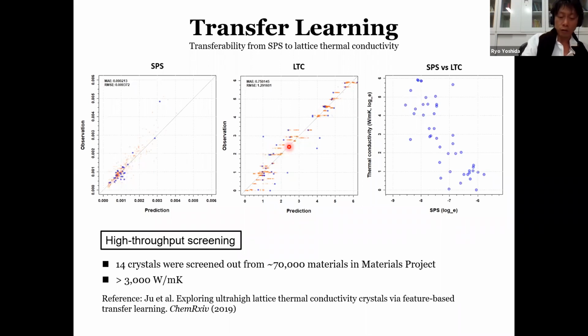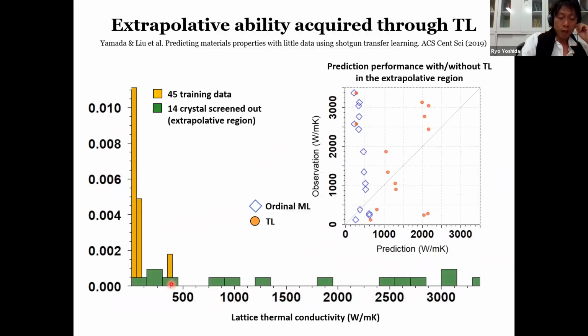Finally, using this model, we performed screening over 70,000 materials taken from public databases, which include real and virtual compounds. We finally discovered 14 crystals. Some of them exhibit very high thermal conductivity, reaching more than 3,000 watts per meter Kelvin. This is one of the successful applications.